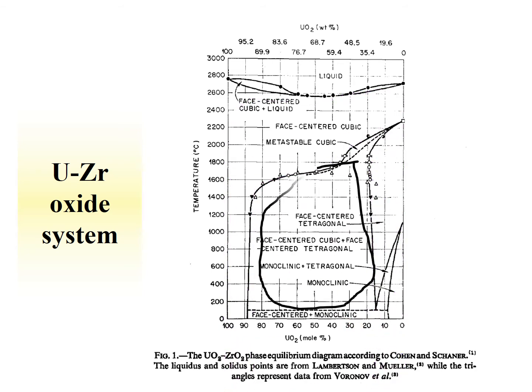Now, in this regime shown here, we have multiple phases formed, face-centered cubic and face-centered tetragonal. So when we start to reach percentages of uranium lower than what's shown on that side of this solid solution regime, we start having mixed species. This is an example of a system that's important for nuclear fuel, as zirconium is a large fission product. It's also been explored for inert matrix fuels, but this system is rather complicated, and you can find different data in the literature.